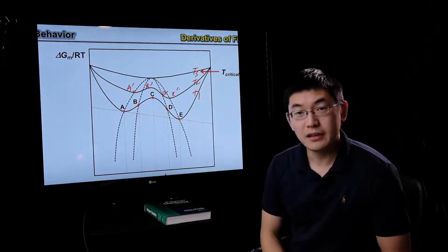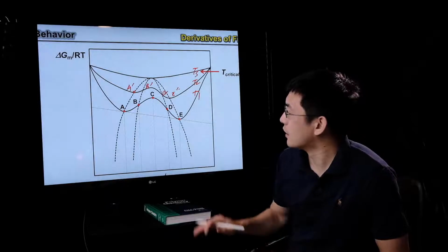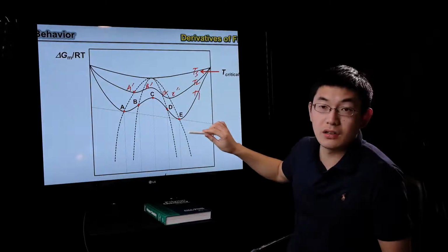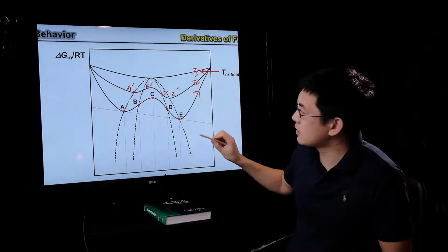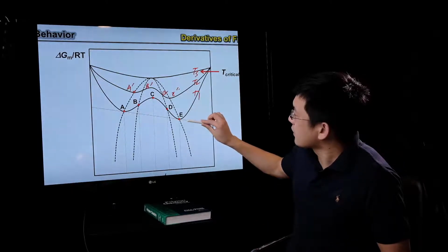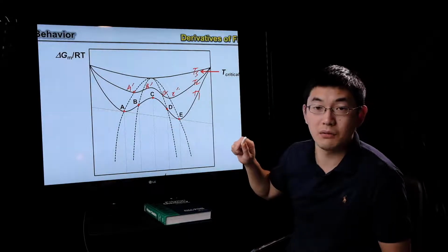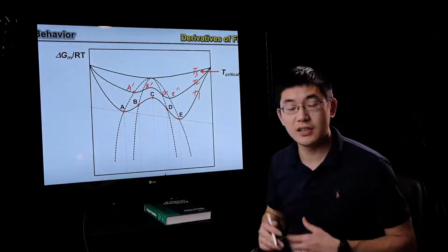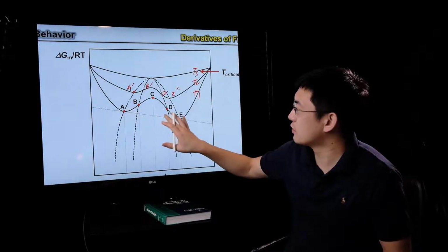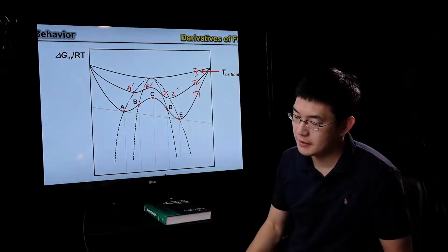So on the phase diagram, we explain what a binodal is, and binodal is where you would get the tangent of this red curve with respect to your delta G curve. It's not the minimal point, so please be mindful of that because they are very different definitions. Okay, so this will be this dashed line tangent with the delta G. And why do we need to worry about tangent? In this case, this will make sure that when you have phase separation, it can phase separate into these 2 phases, and their total system energy would have the maximum drop.